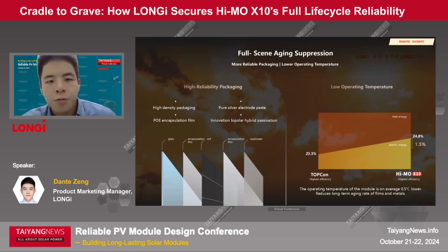And for the electrodes, we use pure silver, because the TOPCon's DH issue partly comes from them not using pure silver, but using silver doped with some aluminum to achieve better electrical connection. But it also leads to higher corrosion issues. But for our BC, we adopted pure silver electrode paste for both positive and negative. So we do not have that issue. Also for our bipolar, as I mentioned before, we do not have that many leakage channels, and we have a very high open circuit voltage. And for this part, we can guarantee the reliability on the packaging side.